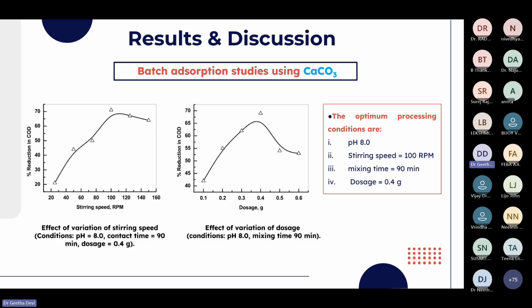This is the batch adsorption, where stirring speed was varied, and also the dosage was varied. The optimum processing conditions were obtained at a pH of 8, a stirring speed of 100 rpm, a mixing time of 90 minutes, and a dosage of 0.4 in the case of calcium carbonate.